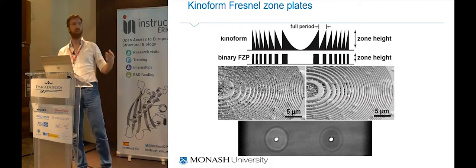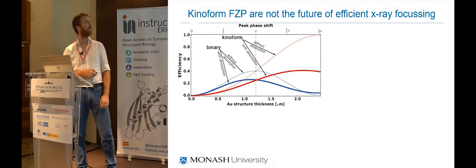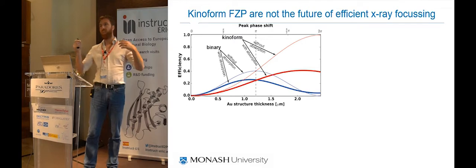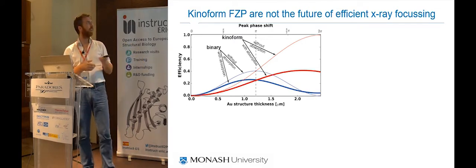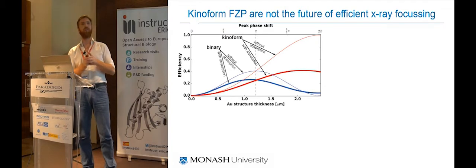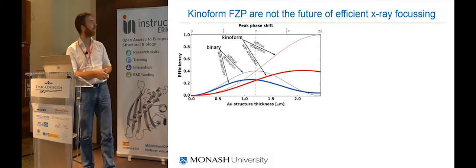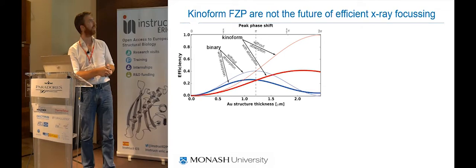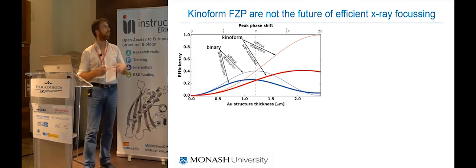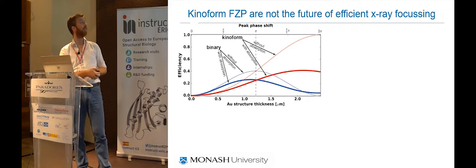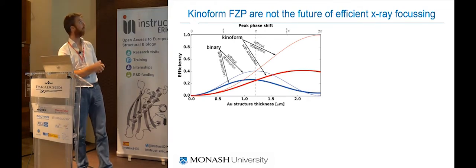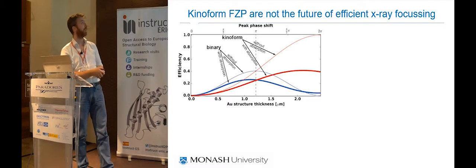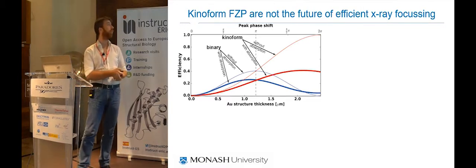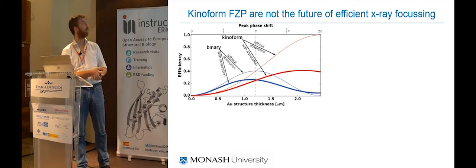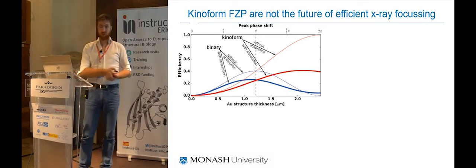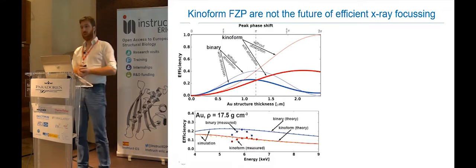So you should not be doing Kinoform lenses, because for a very long time the math that was used was wrong, and they did not take into account absorption, unfortunately. If you design your zone plate to induce a 2-pi shift in the phase, and you don't consider absorption, you will get 100% efficiency. But the truth is that absorption kicks in, because photons will get absorbed, so you will get nothing more than 30%. So it's not much better than what you normally get already with binary zone plates.